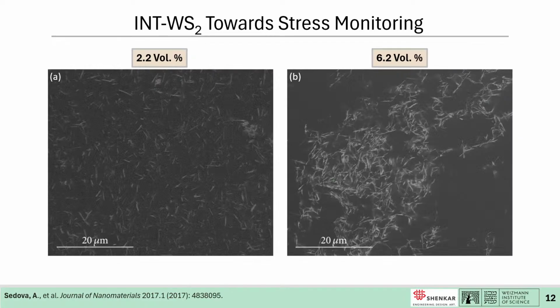So we started to do similar work as done with carbon nanotubes, dispersing the nanotubes in a polymeric medium in order to try to achieve percolation, a continuous network of the nanotubes where electrons can hop from one nanotube to another. But unfortunately, we didn't succeed that way. The nanotubes were encapsulated in the polymer, and the conductivity was not happening.